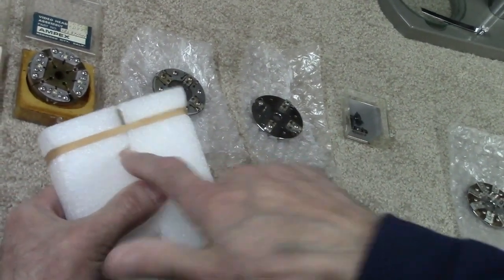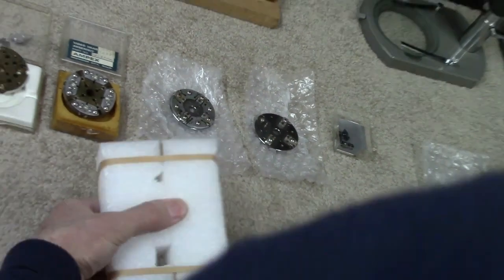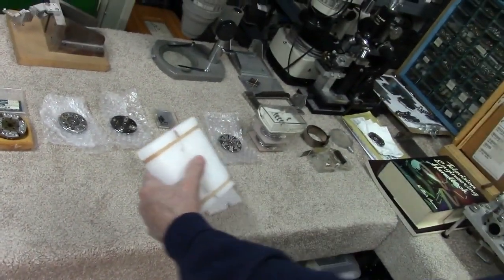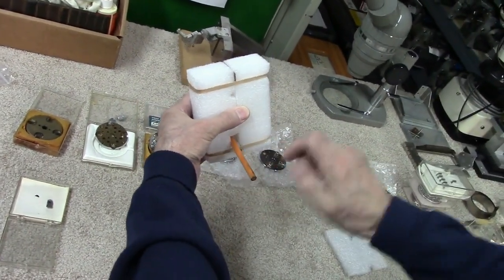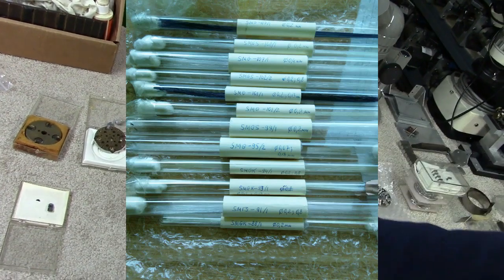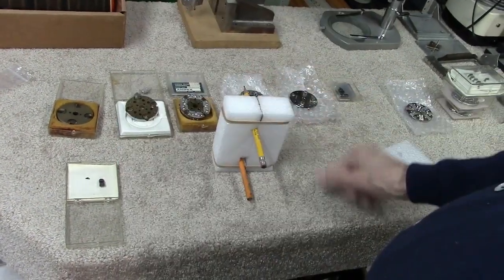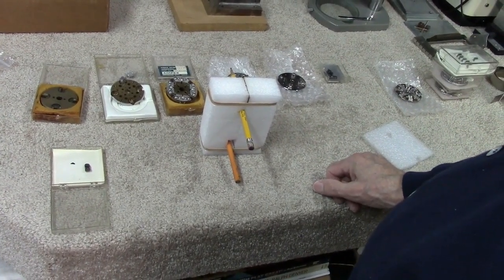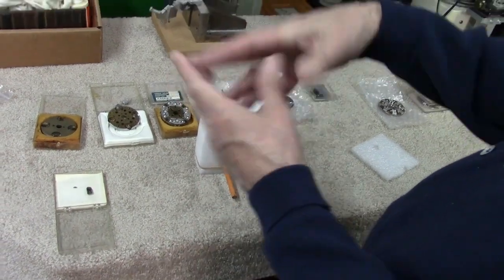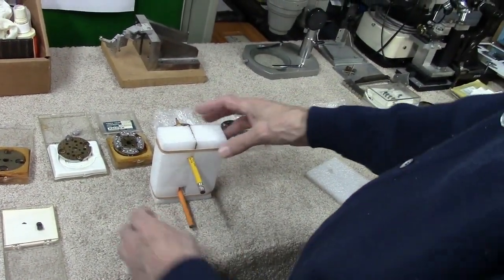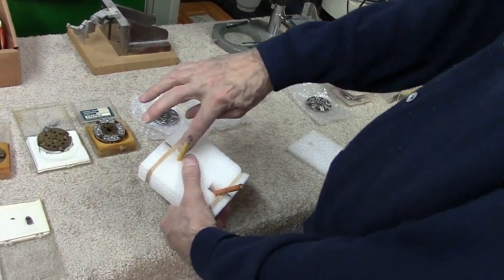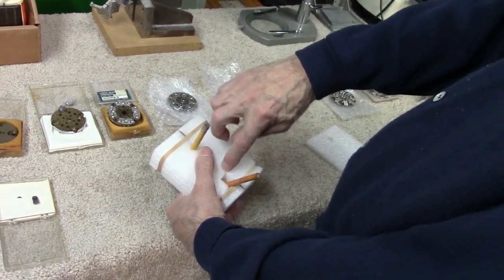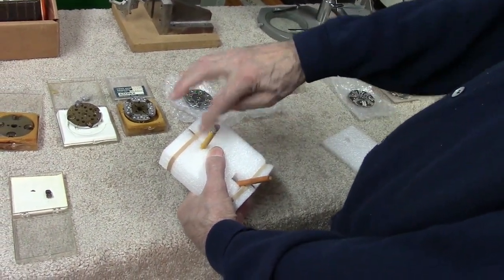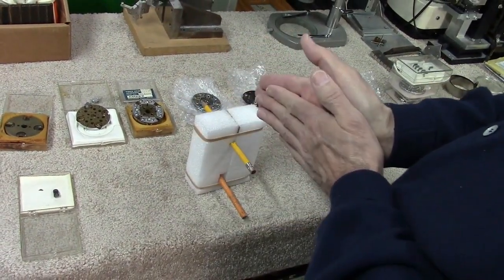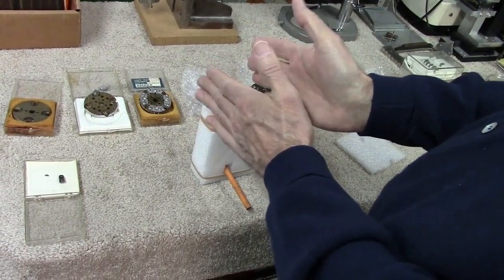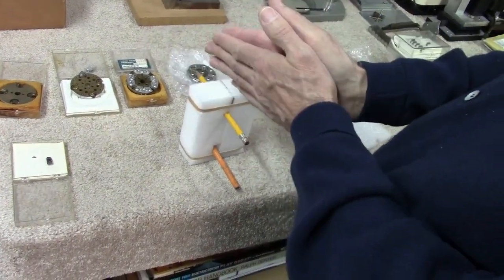And then into the winding window in the back gap, we would insert our glass rods, our brazing rods, and we would then put this in a vacuum furnace and bring it up to a temperature where the glass flows, and through capillary action it'll be sucked back into these gaps, these little voids between the two pieces. And so that forms a glass gap and joins these two pieces together. Bonds, I should say, glass bonding.